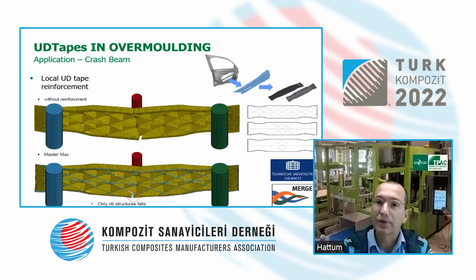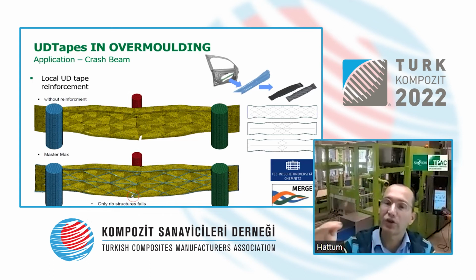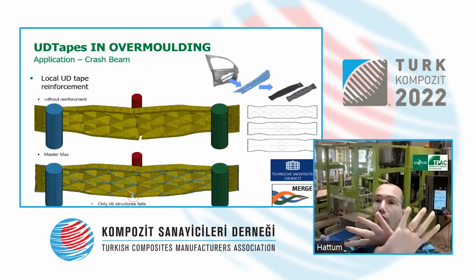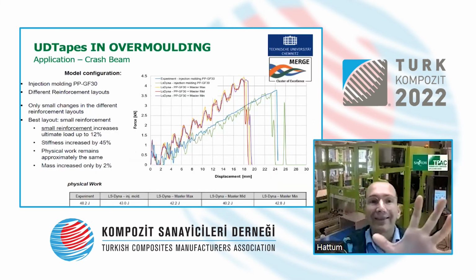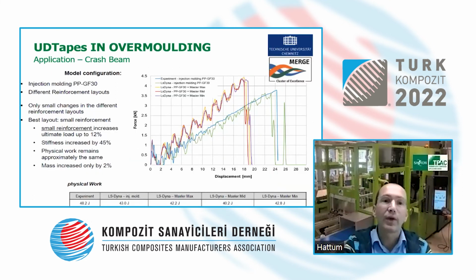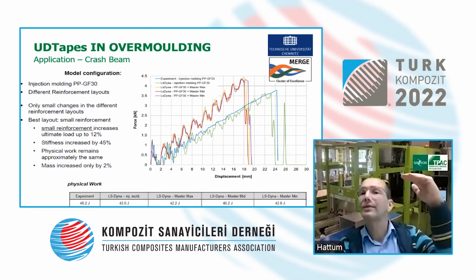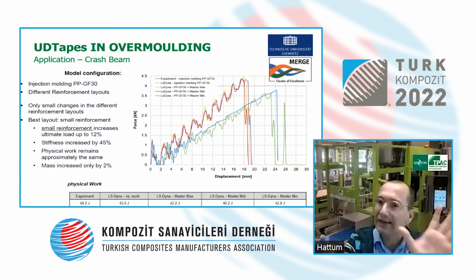out of UD tapes. We tried 3 different versions that you can see on the right hand side in the center. Fully reinforced, only the center section, or absolutely minimized just in the middle. And if we then look at the performance, we can find that by just adding a small reinforcement, we can get a 10% load increase of exactly this structure.